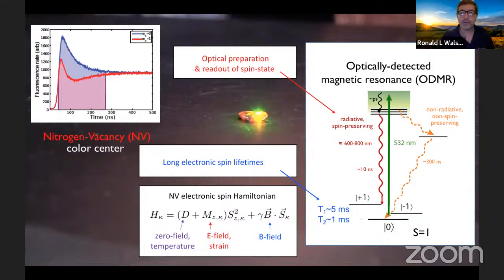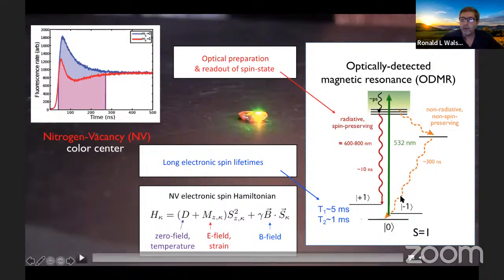Then you know you're in ms equals 0. And if you want to, you can switch to ms equals 1 or -1 with resonant microwave pulses, or you can do any kind of experiment. You start in ms equals 0. So that's one of the key things. The second one is the difference in the average fluorescence rate between ms equals 0 and 1 or -1 during this first few hundred nanoseconds, as shown in this block diagram here. The difference in the average total amount of photons that are coming out on the blue curve and the red curve, they're significantly different.